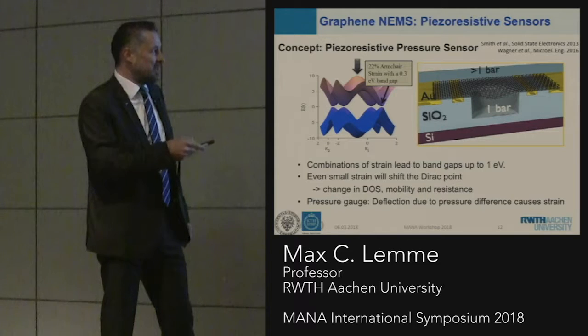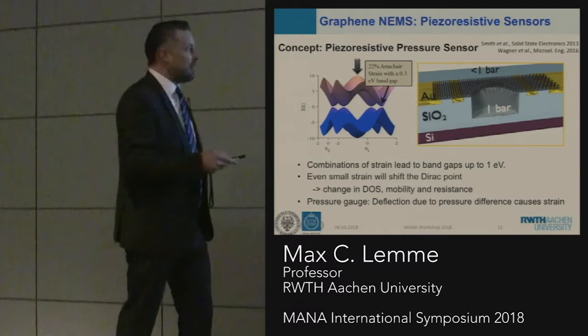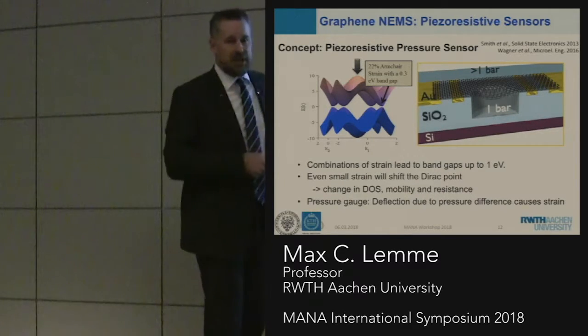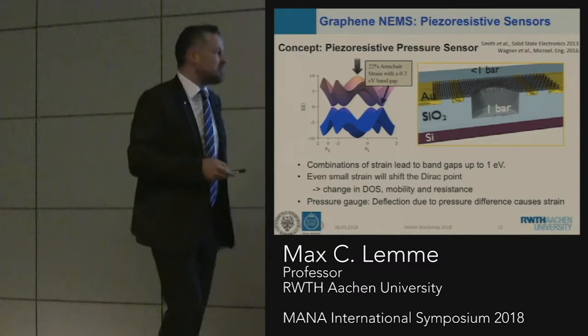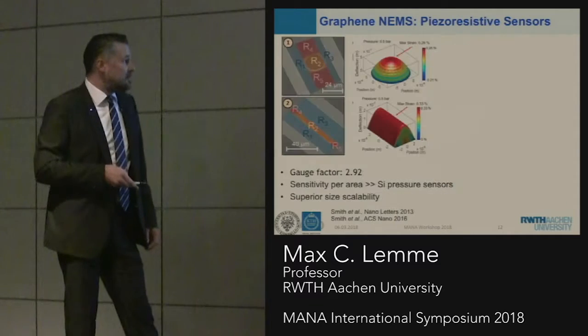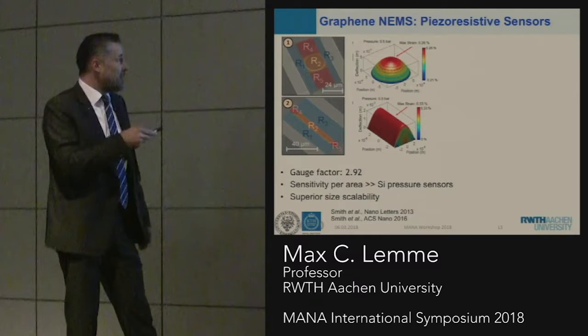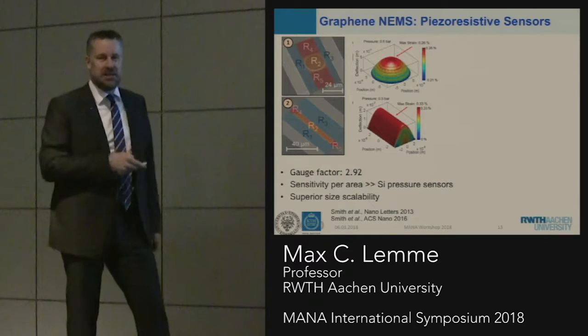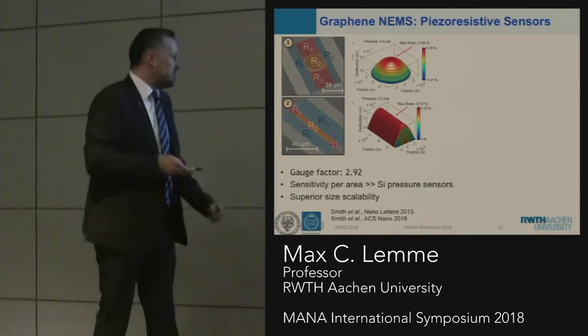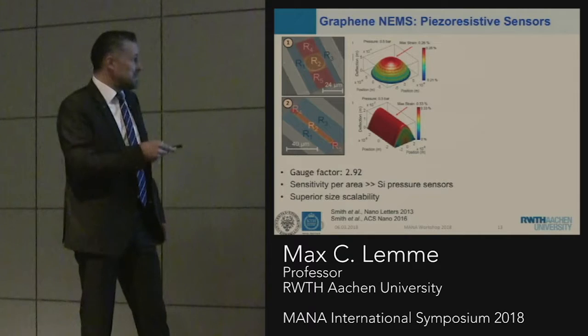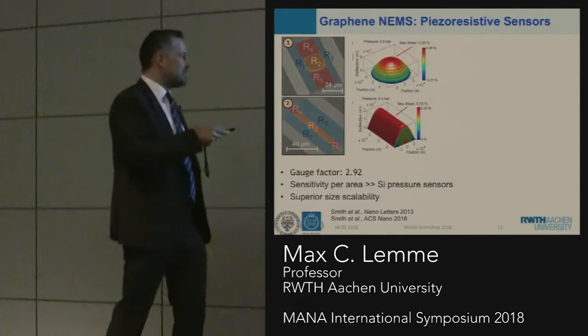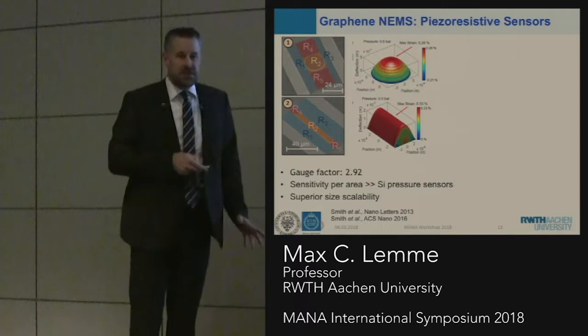So we have a membrane that is ultimately thin, and it acts at the same time as the membrane and the transducer material. We did this for round membranes where we have more or less radial or biaxial strain, and then also for very long, wide and narrow membranes where it's uniaxial strain.